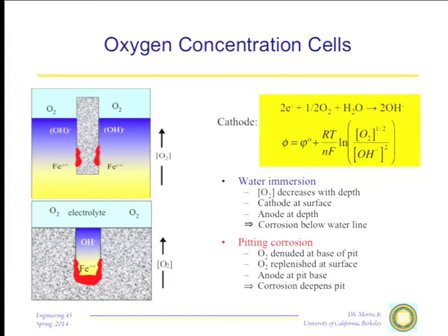Why is that? The reason is that the ordinary reaction consumes oxygen. If you go down to the bay, the oxygen is coming in from the atmosphere. So the layer of water right next to the atmosphere is relatively rich in oxygen. Since it's rich in oxygen, that's the cathode in the reaction. Slightly below that, where the oxygen is leaner, that becomes the anode in the reaction. So the oxygen-rich material corrodes the oxygen-poor material. And that's why the corrosion almost always occurs just a bit below the surface. And that is a source of a huge problem.